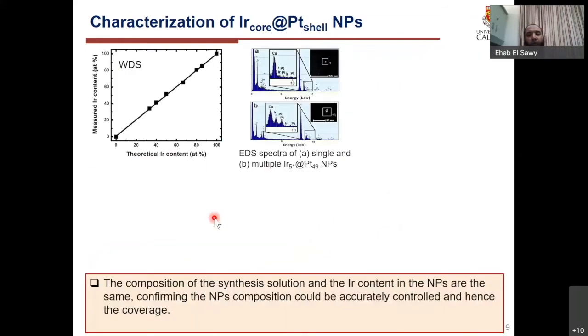So in this slide, I'm showing the WDS measurements. The reason we use WDS instead of EDS is that platinum and iridium are very close to each other in mass number, so WDS is more accurate. When we compare the theoretical iridium content based on the solution with the iridium content based on the WDS measurements, we found a straight line. That means we have full control over the composition of the nanoparticles.